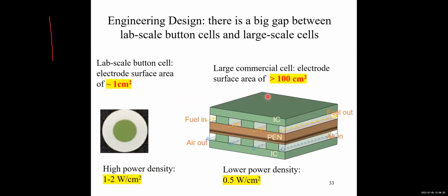But for large-scale cells with a surface area of more than 100 centimeters squared, the power density is much lower, roughly around 0.5 watts per centimeter squared. This is a typical planar large-scale cell, and normally we need to integrate multiple cells to form a stack in order to increase the voltage and power output. This is the interconnector that collects different cells, and this is the rib of the interconnector.